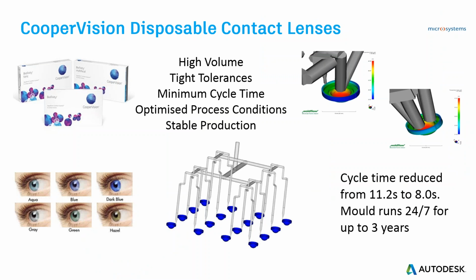So one such company, Cooper Vision, they're already running a high cycling mould. They're running at 11.2 seconds. They wanted to get this down to 8 seconds. This would have a significant effect on output. So using Moldflow, they were able to pay attention to the mould cooling, and they got cycle time down to 8 seconds. These moulds run for 24 hours, 7 days a week for 3 years. So the quality has to be good, making sure that the modified cooling doesn't adversely affect the components in terms of size and the way it fills.